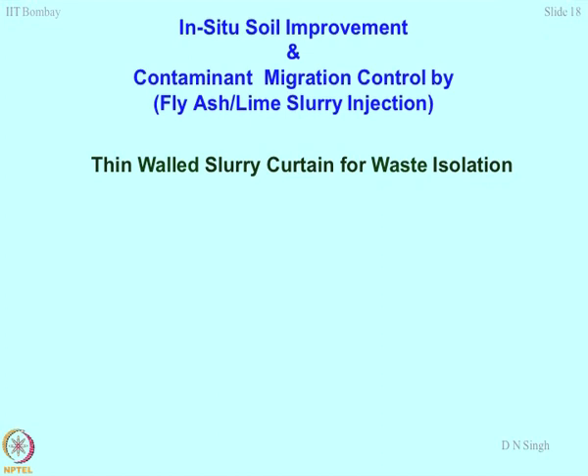In situ soil improvement, for which you can use fly ash slurry mixed with cement and lime, and then you can inject it in the ground. So this forms a good gel, and ultimately you can improve the soil. We are talking about contaminant migration also. So you can control contaminant migration by injecting fly ash lime slurry and making piles into the system or the curtain walls or the grouts. So these are known as thin wall slurry curtain for waste isolation. So dig out a certain portion of the ground and then inject in that slurry of fly ash, lime and cement. So ultimately what you are doing, you are cutting off the contaminated down from the environment.